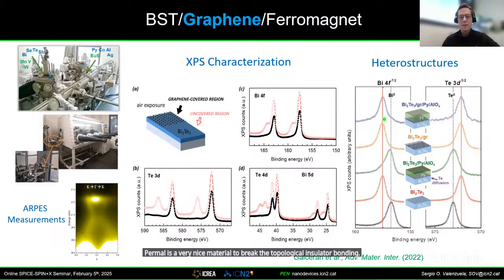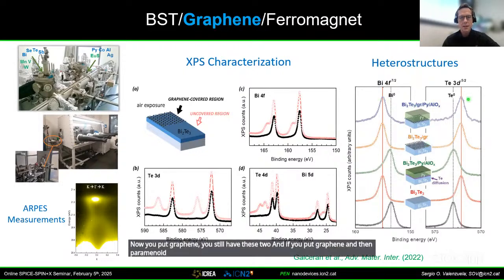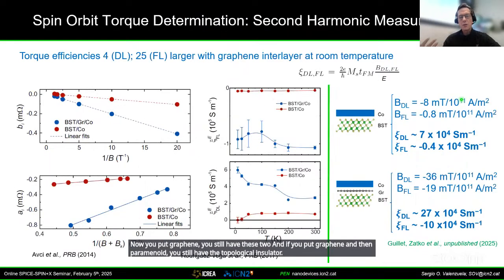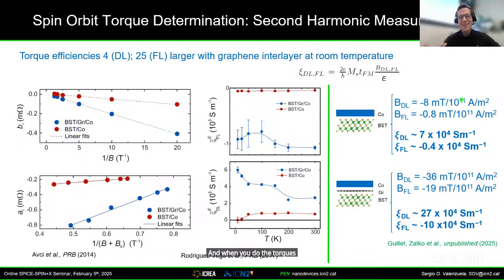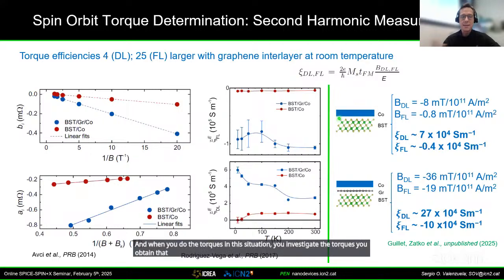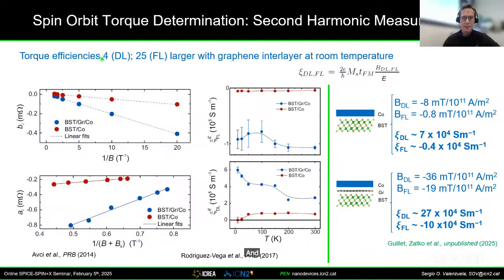Now, if you put graphene, you still have these two, and if you put graphene and then permalloy, you still have the topological insulator. And when you do the torques in this situation, you investigate the torques, you obtain that you can directly compare in the same film what happens in this structure or in this structure, and you see a factor 25 on the efficiency of the torques for the field-like and a factor 4 for the damping-like.